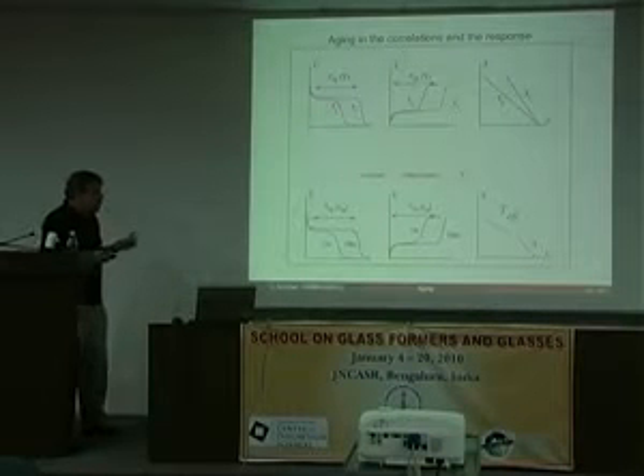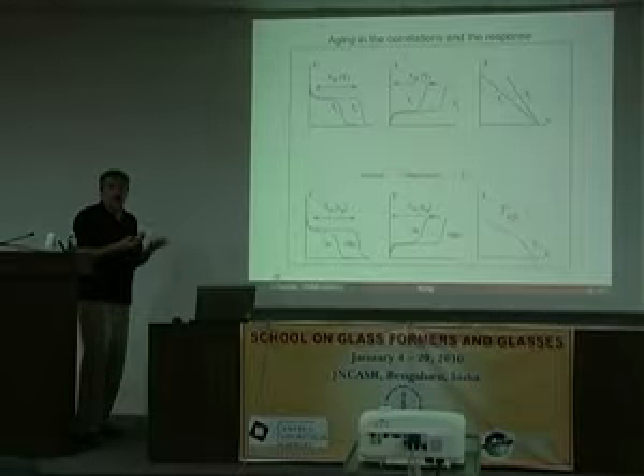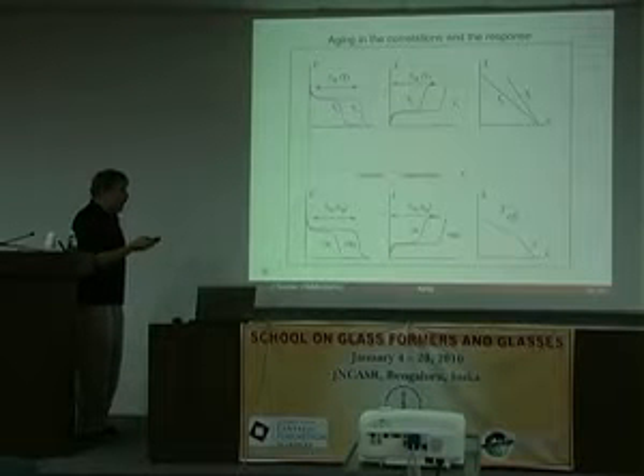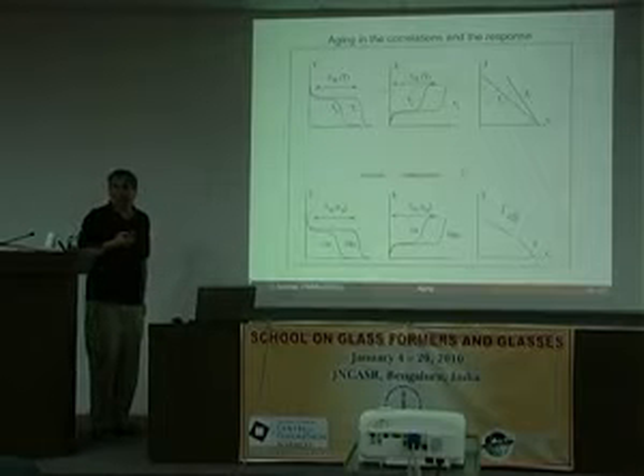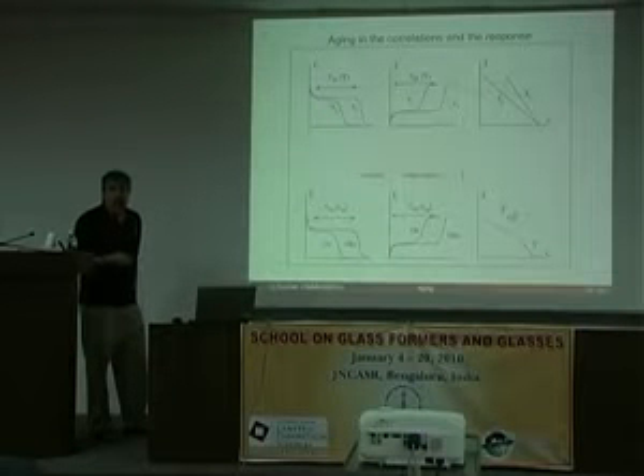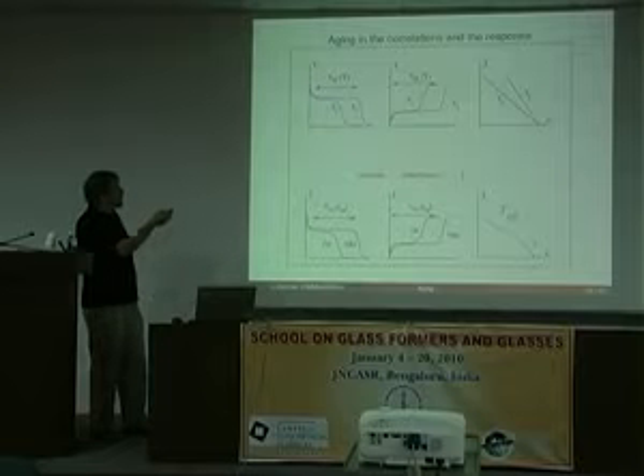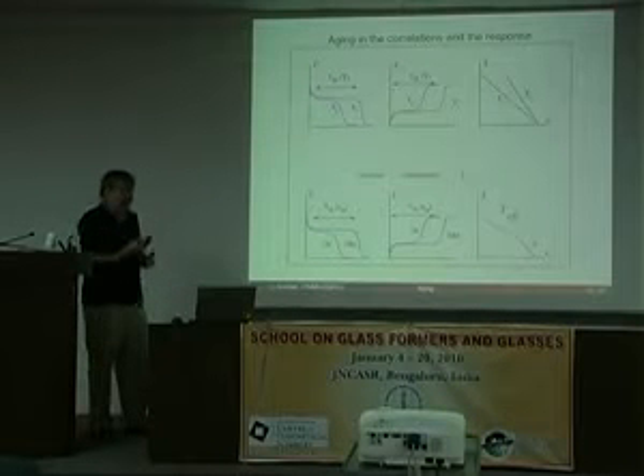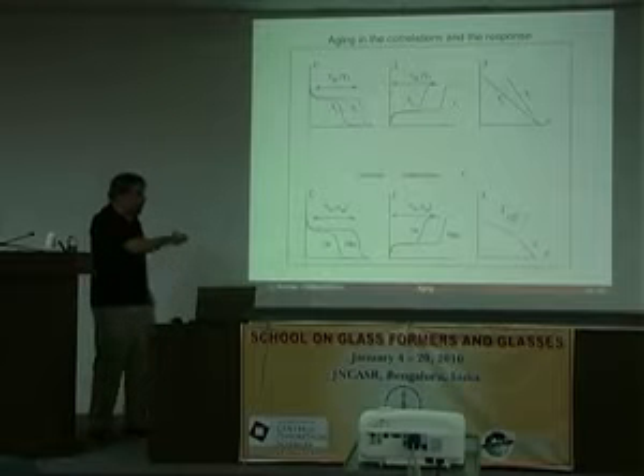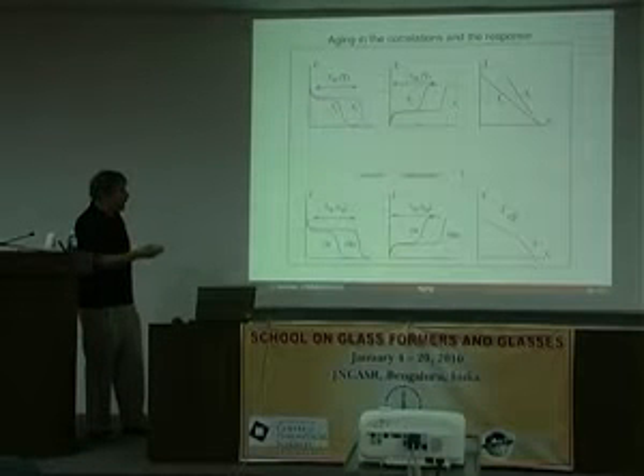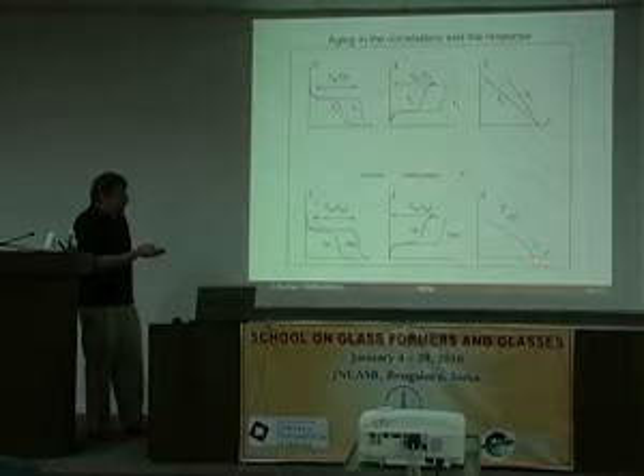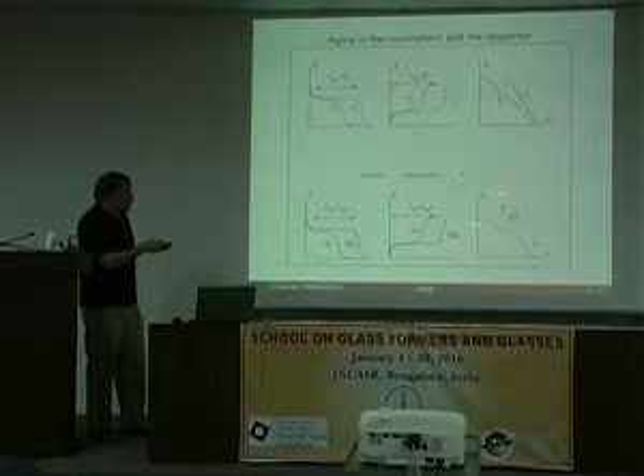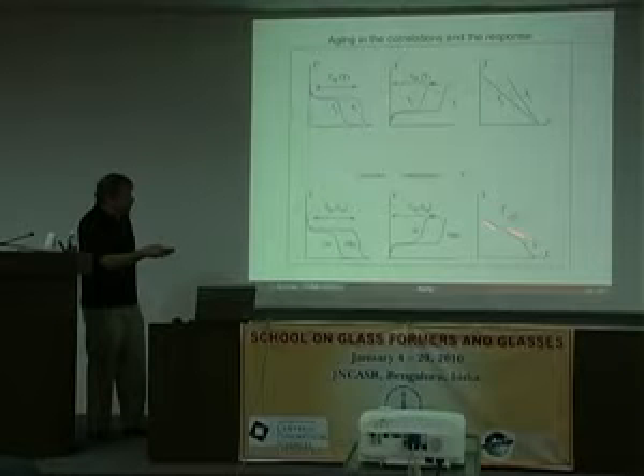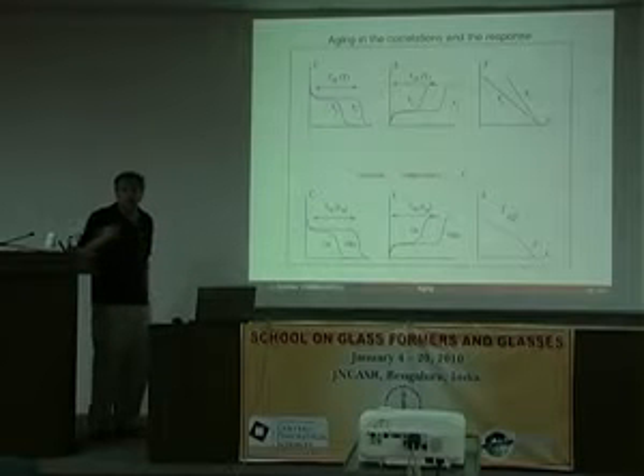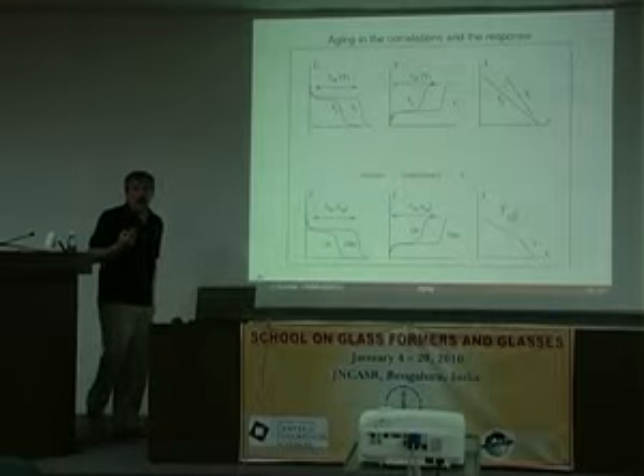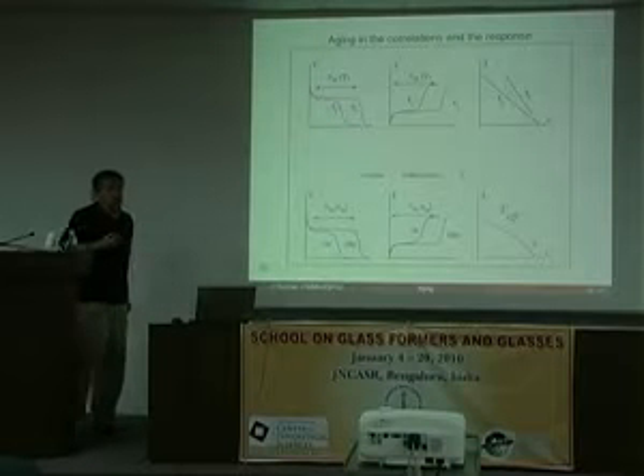So this was a discovery on a model on which you could say everything. And what you get on this family of models, which is crucial, is that for every observable that you do this for, because remember that a correlation can be a correlation of many things, and you only have to choose the appropriate response and put them in relation with one another. For every observable, the length of these segments may change, but at the same corresponding times you get the same effective temperature for all observables. So this is something that you expect of a temperature.